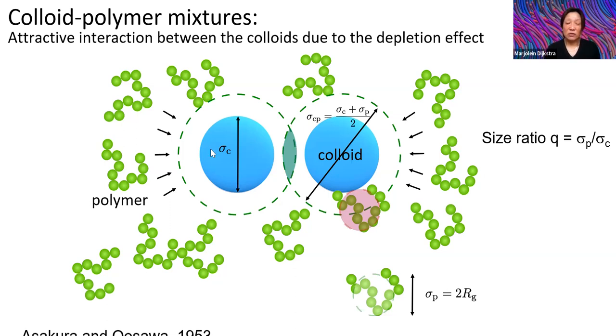So in this case, we have two colloidal particles. One can easily draw the regime where the center of mass of this polymer coil cannot come. So this is basically the dashed circles here. But if the colloidal particles come close to each other, these so-called depletion zones overlap in such a way that there's more room for the polymer coils. More room for the polymer coils means more entropy. And so there's basically an effective attractive interaction between the colloids, which increases the entropy of the polymers. The range of this interaction is set by the size of the polymers, and the depth of the attraction well is determined by the concentration of the polymer.